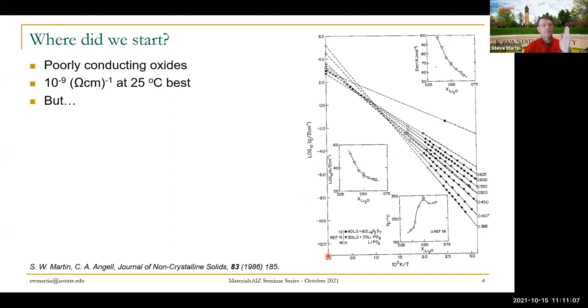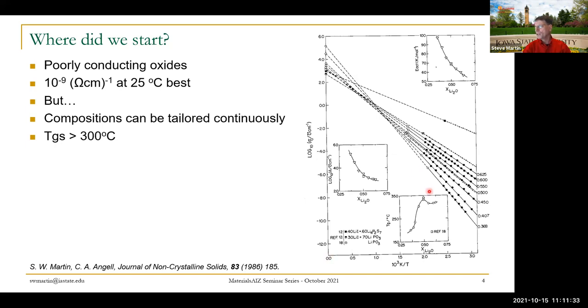So in the separator, of course, which my talk is focusing on, we have to have very high conductivity because every electron has to be matched by a lithium ion. And that lithium ion has to migrate across the cell. So the conductivities have to be very high. But the glasses afford this compositional tailorability. Glasses have often been called the universal solvent. And so you can vary compositions quite dramatically. And you can see that down here in my insert from 25 to 75% in that range. You can triple the concentration of lithium ions. And in doing so, lower the activation energy and rather strongly increase the conductivity.